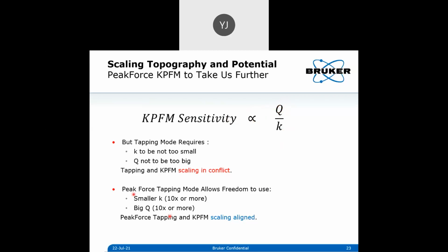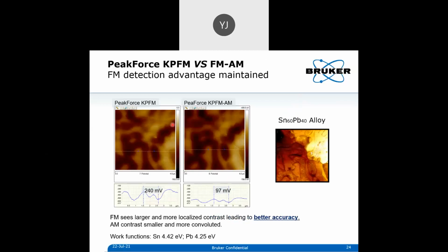But because the PeakForce tapping doesn't really need to be at the resonance frequency of the cantilever, we can use a very, very low K cantilever or a very soft cantilever, at least easily 10 times softer than the tapping mode, right? And you can use at the same time a very large Q. So you can see if you have a 10x factor here, 10x factor here, you can right off the bat improve your sensitivity by two orders of magnitude, right?